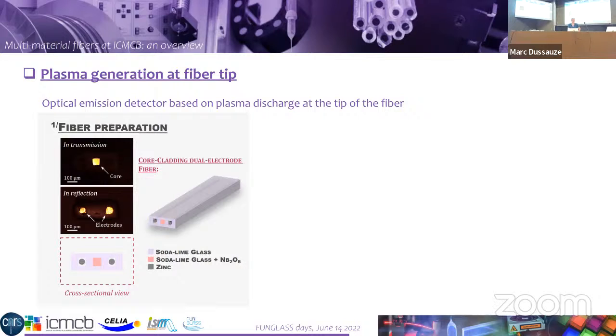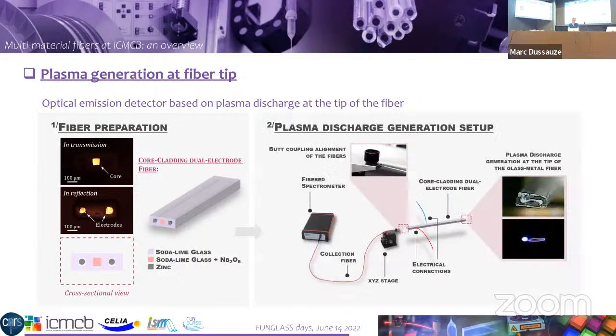So here is a stack and draw preform. This preform is a hollow core preform made of soda-lime glass for the cladding, a soda-lime core doped with niobium oxide to increase the refractive index to have some guiding effects between the core and the clad. And inside were inserted 2 electrodes. And then this preform is drawn into fibers. Here in transmission, we see the core. In reflection, we see the 2 electrodes.